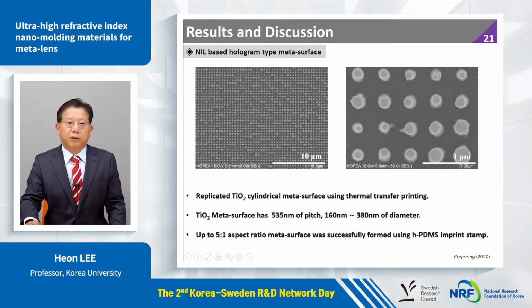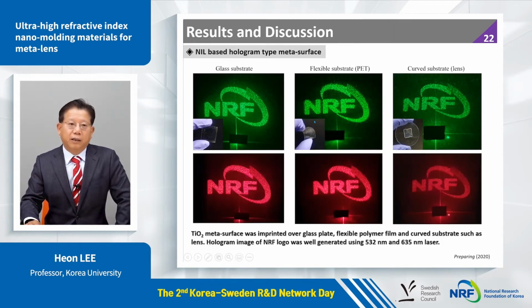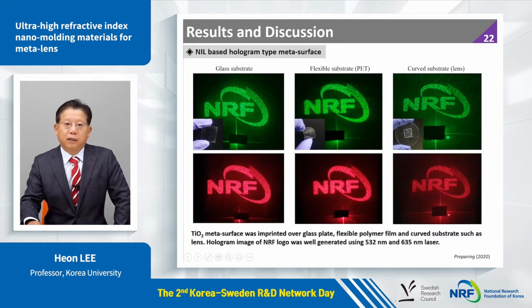And this is the imprinted hologram-type metasurface. You can clearly see the series of nanocylinders have varying diameters. And this is the hologram image. The left one is the hologram metalens formed on a glass substrate. The middle one is formed on a flexible polymer substrate. And the third one is the same thing, formed on the surface of a lens. When using the green laser, blue laser, or red laser, you can clearly see the hologram image.